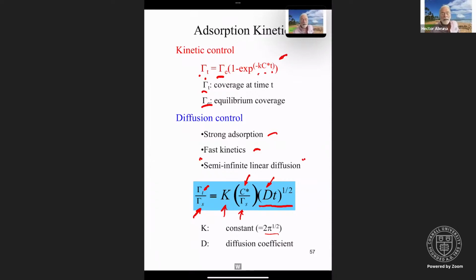Notice also, as I mentioned earlier when we were talking about diffusion coefficients, that very often you end up taking the square root of the diffusion coefficient. So now the value of 9 times 10 to the minus 6 centimeters squared per second makes a little bit more sense.